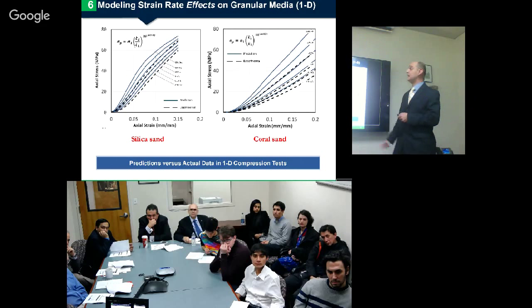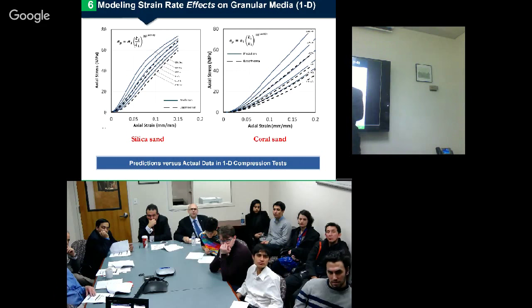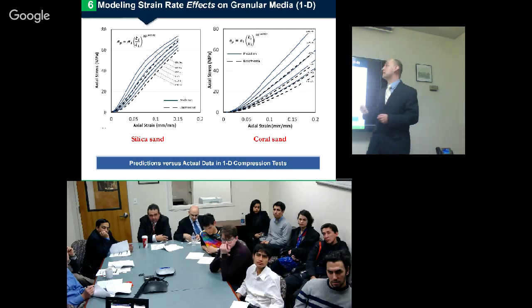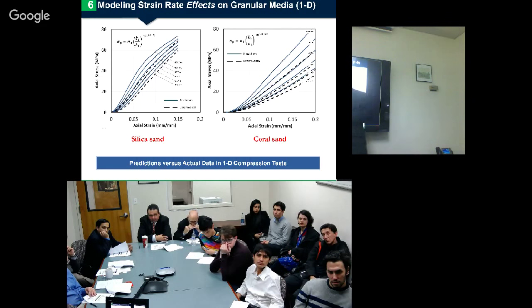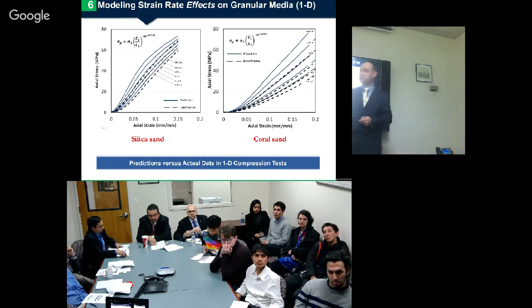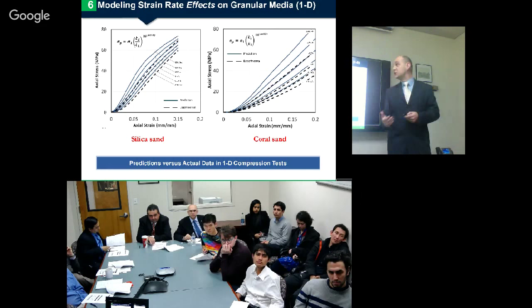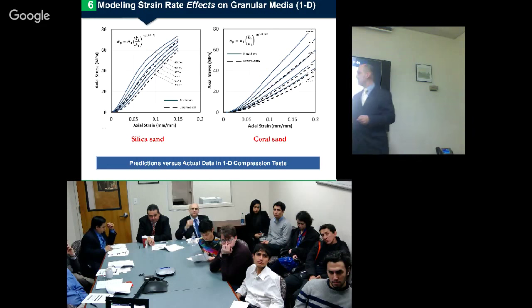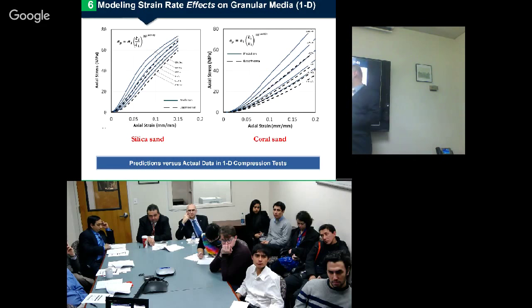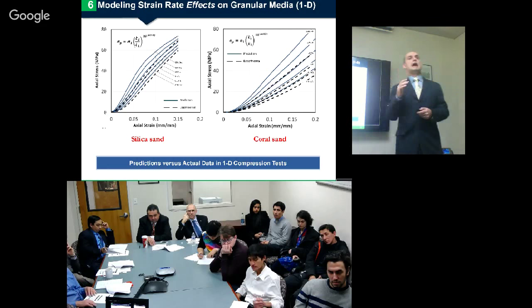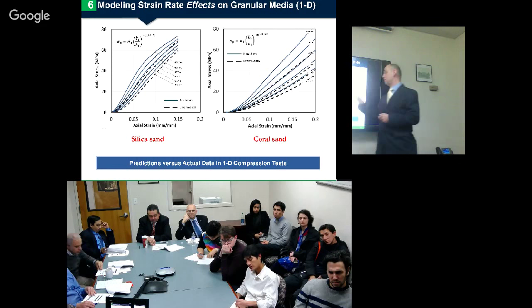But then, at the end, that m value is going to be somewhere here, and we can find out the prediction of sigma p. Sigma p is the prediction of the stress. If we know an existing strain rate, and if we want to predict this axial stress, by using this epsilon, which is the actual deformation, we can make predictions starting from the quasi-static condition, and we can go even higher. So from 0.01, 10% per second, 100% per second, 1,000, and even higher. Obviously, this is going to have a limitation, which I'm going to explain later on.